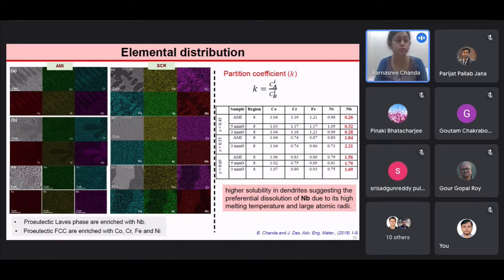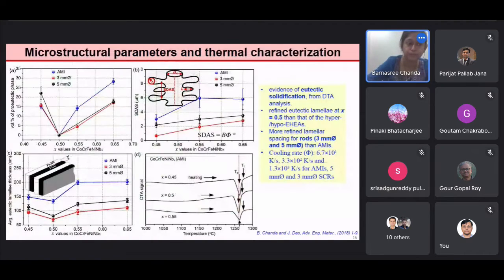to the preferential dissolution of niobium, due to its high melting temperature and large atomic radii among all the added elements. As we see in the optical microscopy and scanning electron microscopy, there is a different distribution of proeutectic phase in the eutectic matrix. Therefore, we have quantified those microstructural parameters as volume percent of proeutectic phase. The plot shows the variation of the volume percent of proeutectic phase with the niobium addition.